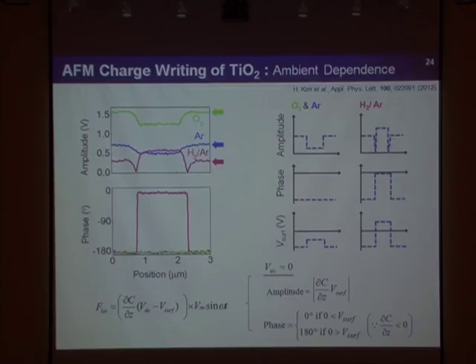In this kind of EFM images, the amplitude and phase correspond to these quantities. The amplitude gives us information about the magnitude of surface potential, and the phase corresponds to the polarity of surface potential. So only in the hydrogen ambient is the polarity of surface potential changed.